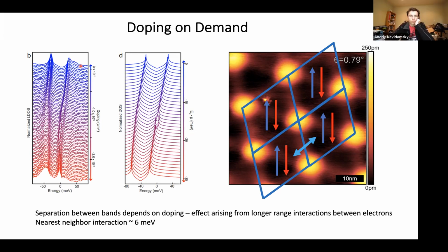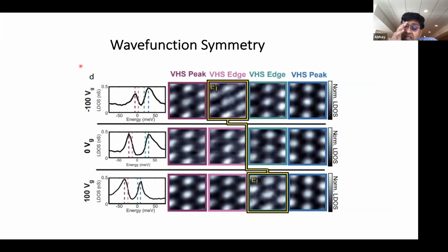Thank you. Okay, so in this experiment, we happened to notice something interesting, which is the following. If you measure at an arbitrary doping what the local density of states looks like, then you would notice that the local density of states looks approximately threefold rotational symmetric. And this is at different energies for a given value of doping. So at this particular value of doping, let's stick to this particular value of doping, which is charge neutrality.